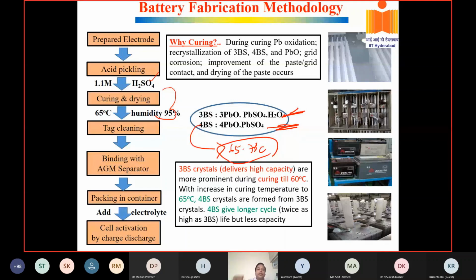If you get a chance to go to any industry, you will see their chambers are like 7-8 feet, a trolley can go inside. The electrodes will be stacked into the trolley, and they put it into the humidifier chamber with 95% humidity. You should not have cracks. So it takes around 24 to 48 hours for the curing action.